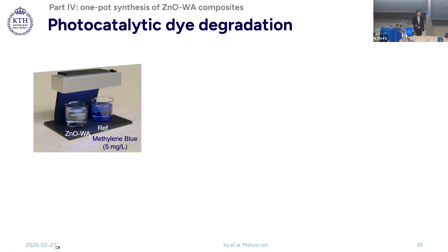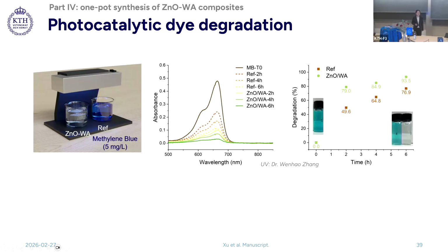The obtained composite demonstrates photocatalytic degradation of methylene blue under UV irradiation. With the presence of the zinc oxide wood aerogel composite, the dye degradation efficiency could reach almost 80% within the first 2 hours, outperforming the 50% of the reference. After 6 hours, the dye degradation efficiency could reach 94%, showing the photocatalytic efficacy of the composite in dye degradation.